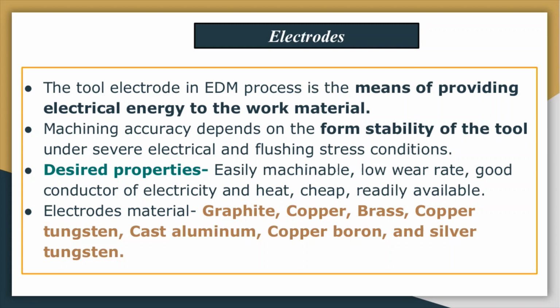Out of that, graphite is easily machinable, has a low wear rate and high conductivity, but there is a main problem with graphite. Although it has low tool wear at high surface finish and high material removal rate, brittleness is the undesirable characteristic, because of which it is prone to breakage. It is a very brittle material, so with a very small force it breaks. That is the main problem of using graphite. Another is copper and brass, which have high stability and relatively low wear rate. Copper tungsten has a low wear rate, although it is expensive and cannot be machined easily into shapes.